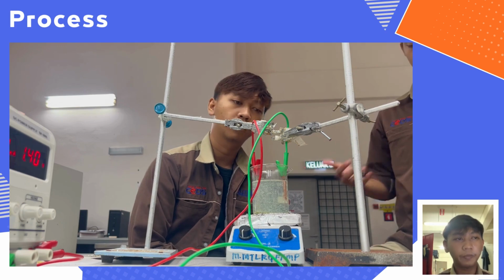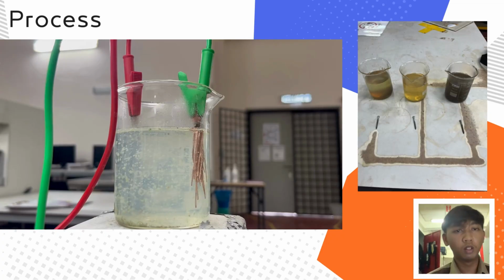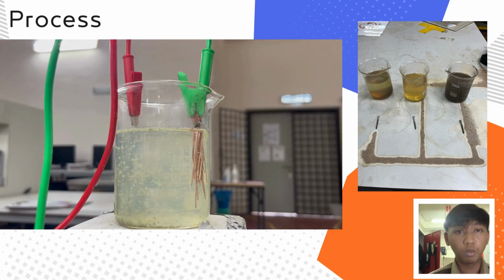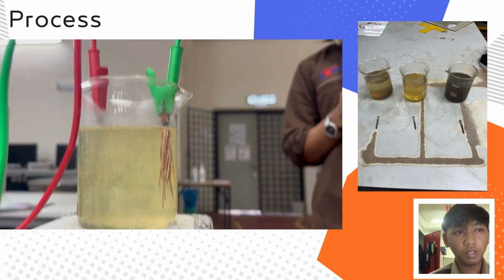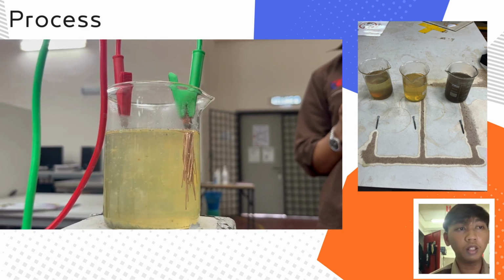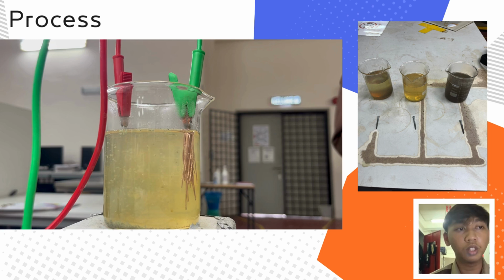After finishing the setup, so this is the electroplating process in 10 minutes. As we can see in the result, the higher the temperature that we use, the darker the yellowish color. So we can see here, from the left picture is room temperature, then 40 degrees Celsius, and lastly is 60 degrees Celsius. We can see that the 60 degrees Celsius solution is darker than the room temperature solution and 40 degrees Celsius solution.